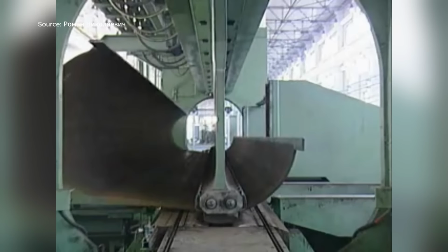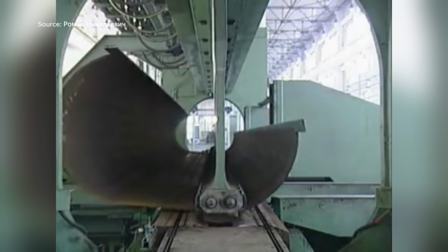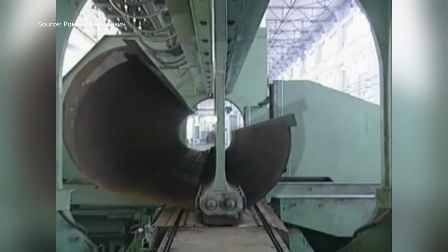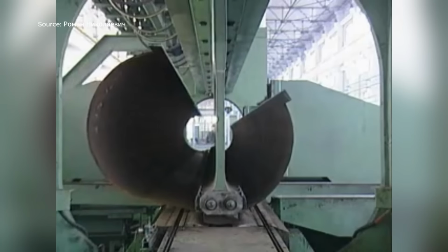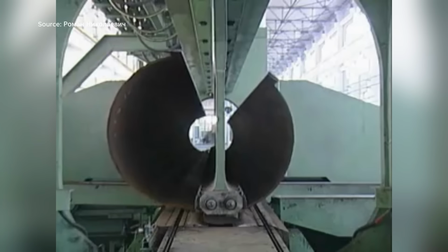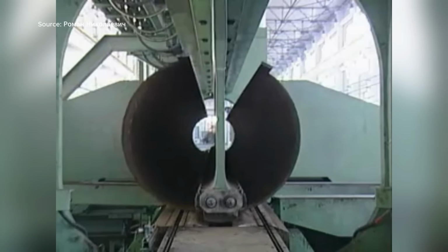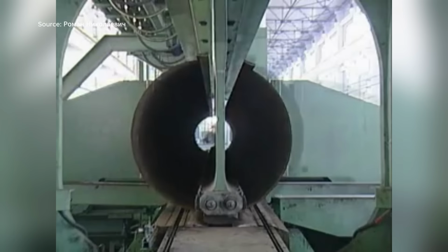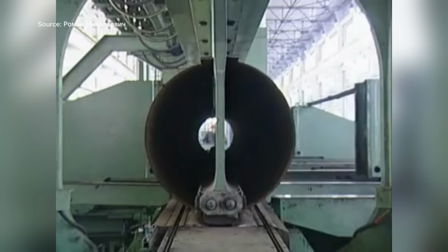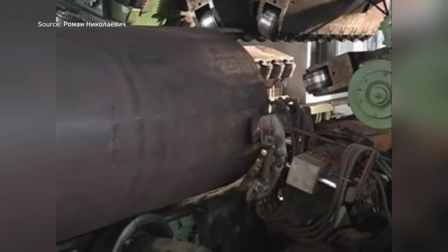The plate passes through a 3-roll bending machine, gradually turning flat steel into a complete pipe shell. After bending, the open seam is tack-welded to lock the shape. The pipe is then rotated and clamped for precision submerged arc welding, delivering deep uniform welds along the seam. Multiple sensors monitor temperature and arc stability throughout the welding sequence.